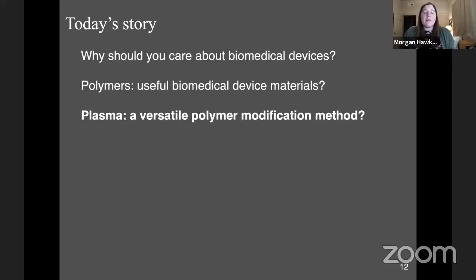But what I was illustrating there with the different parameters that we can change is that we have a lot of knobs to turn and buttons to push, so to speak, and literally, in terms of controlling what those gas phase species are and what their energies are, that can then in turn change what the surface looks like. So a lot of what we do is, for example, taking that water plasma precursor, what would happen if we used a higher power versus a lower power? Well, we do see differences in those surfaces.